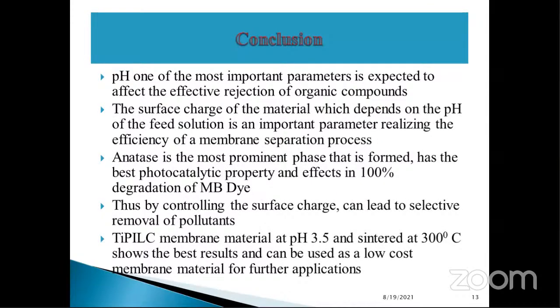So in conclusion, I would like to summarize. As we have seen, pH is one of the most important parameters that is expected to affect the effective rejection of organic compounds. The surface charge of the material is very important. It depends on the pH of the feed solution, and is a very important parameter for realizing the efficiency of the membrane separation process. Anatase is the most prominent phase that is formed, and it has the best photocatalytic activity, and that is why it effects 100% degradation of the MB dye. So thus, by controlling the surface charge, it can lead to selective removal of pollutants.